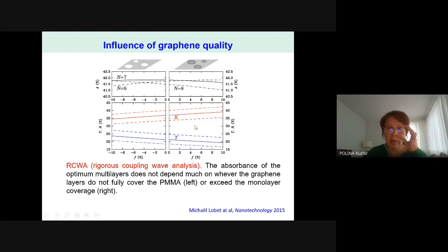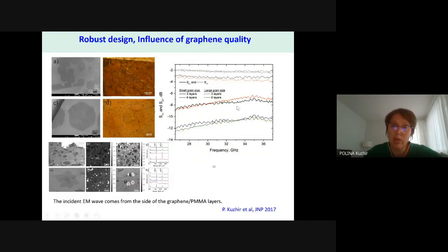This isn't just theoretical estimation using rigorous coupled wave analysis, it's also the result of our experiments comparing graphene composed of two different grain sizes, small 20 microns and large 400 microns. The number of defects is very different in these types of graphene, since defects are essentially the grain boundaries. We see that for the optimal configuration of 3 to 6 layers of graphene, there's no difference in electromagnetic response, both theoretically and experimentally.